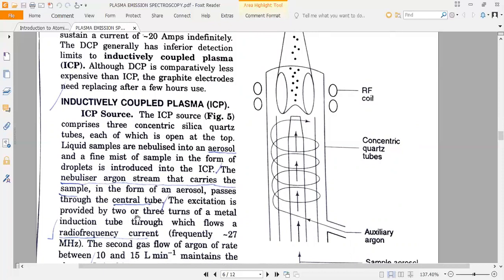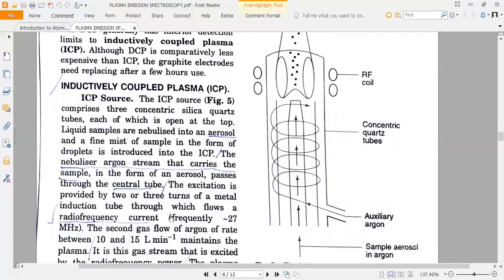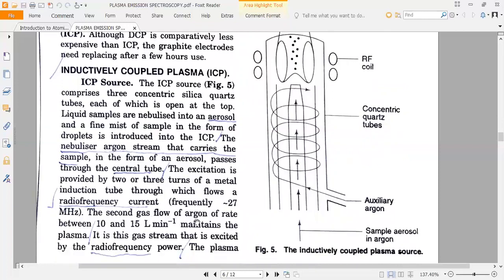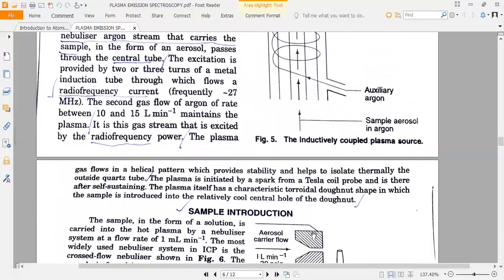The excitation is provided by 2 or 3 turns of metal induction tube through which flows a radio frequency current. Its frequency is around 27 megahertz. The second gas flow of argon, at a rate of 10 to 15 liters per minute, maintains the plasma. It is this gas stream that is excited by radio frequency power. Gas flows in a helical pattern which provides stability and helps to isolate thermally the outside quartz tube.